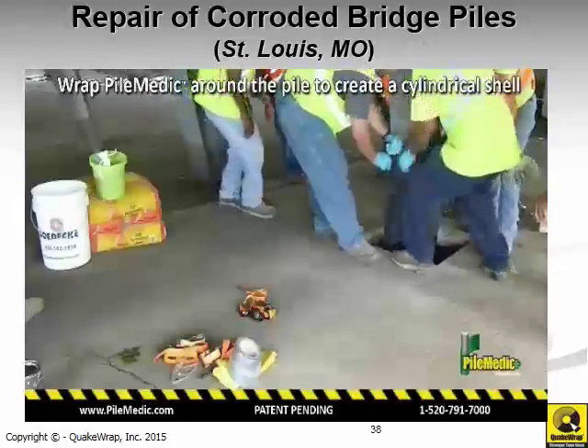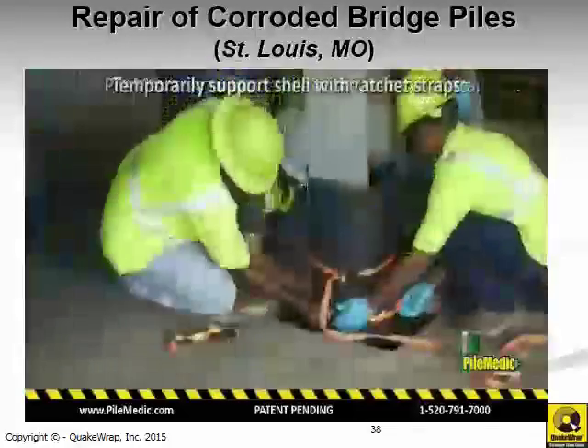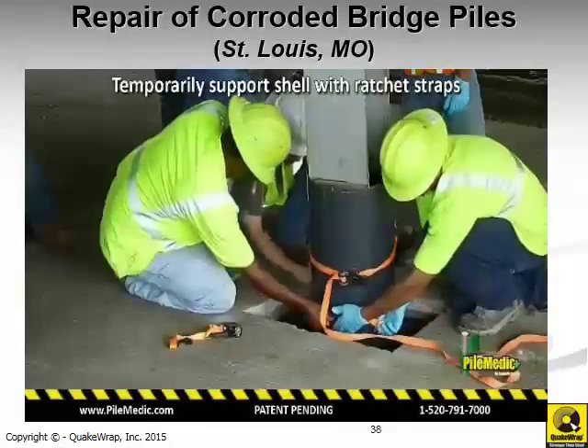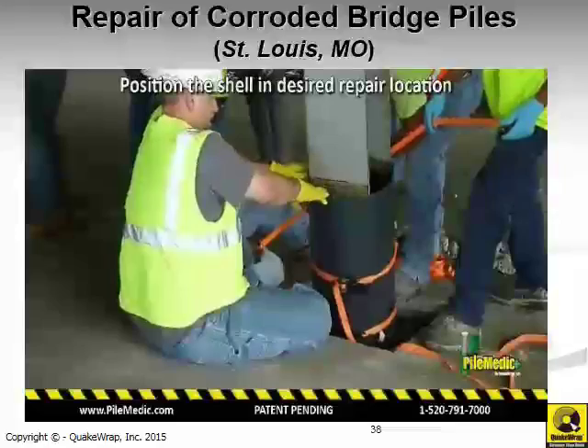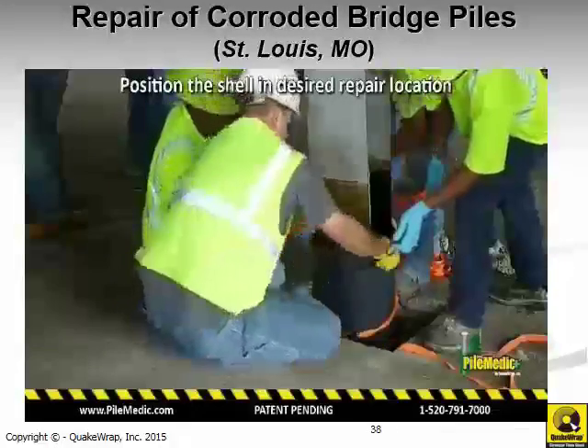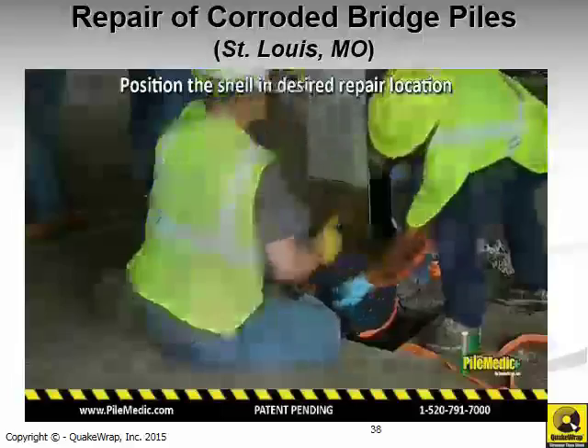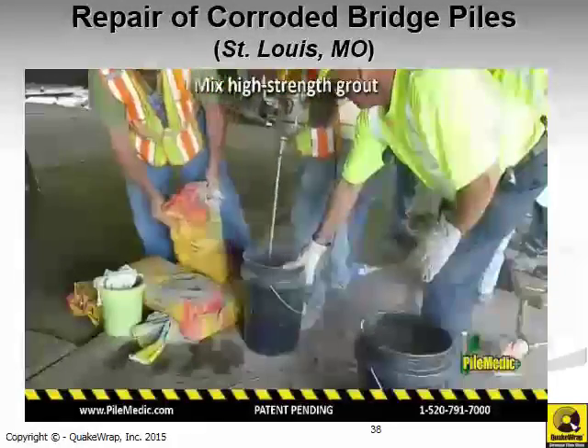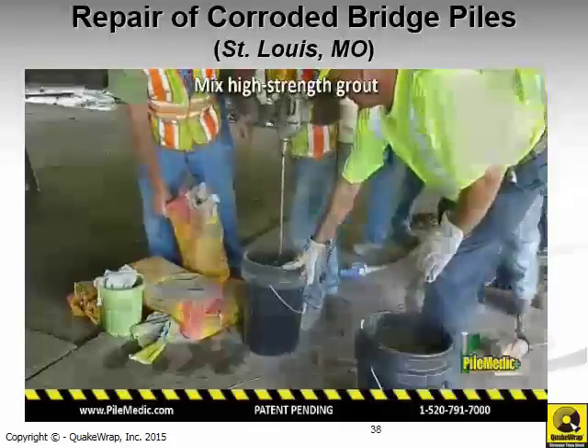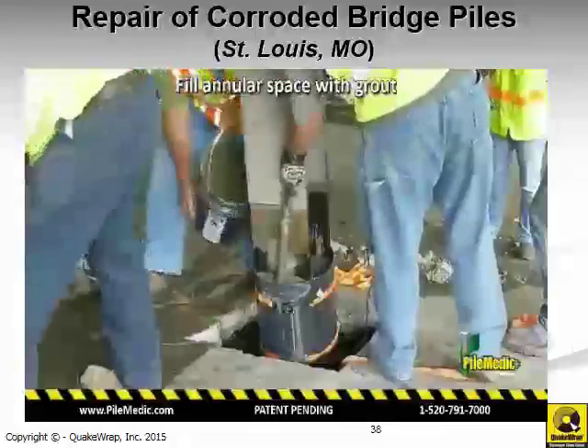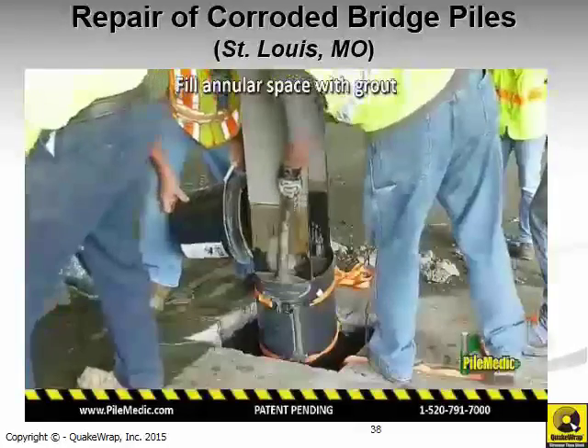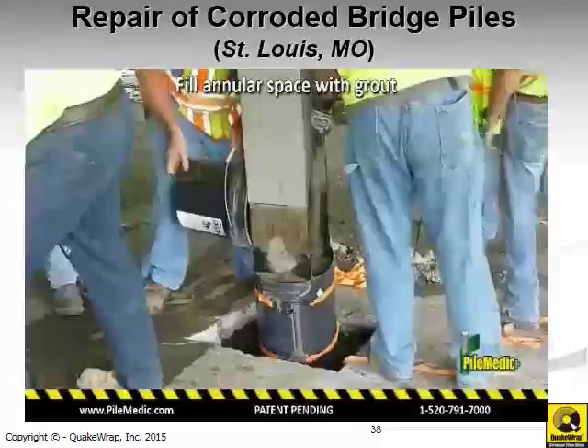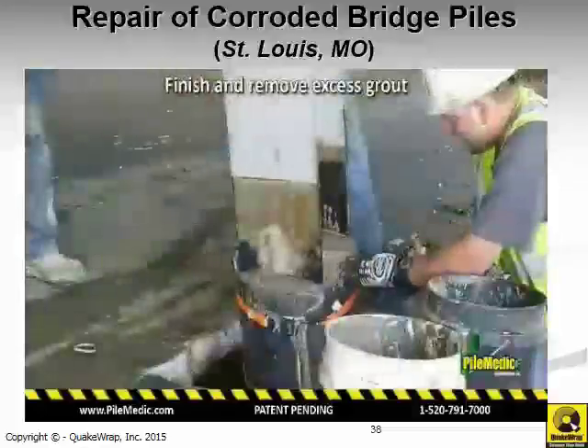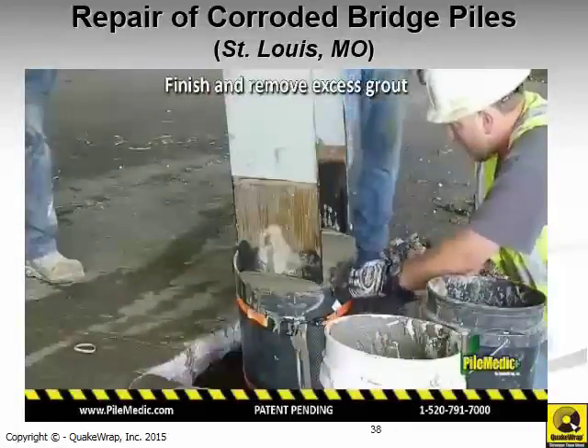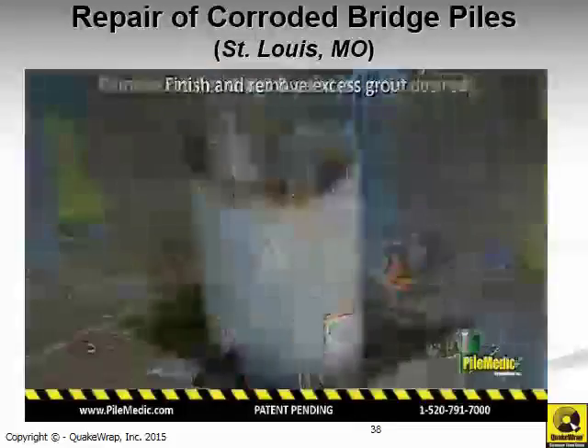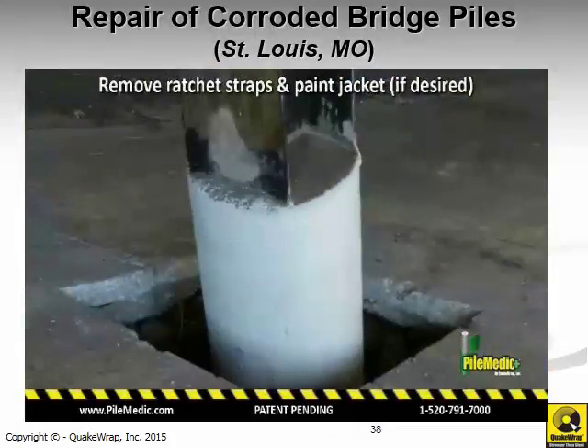Temporarily, this jacket can be held together with ratchet straps, and the size of the column can be adjusted if needed, and it can also be pushed up or down. In this case, they're pushing it down to the sand bed at the bottom of the footing. And then the annular space between the column and the PileMedic jacket is filled with grout. If necessary, additional reinforcing steel can also be positioned in that area to fill that annular space. So very effectively and quickly, columns like this can be repaired.